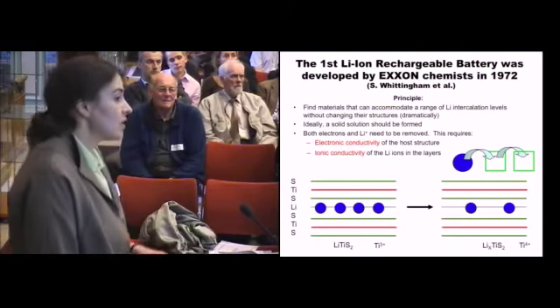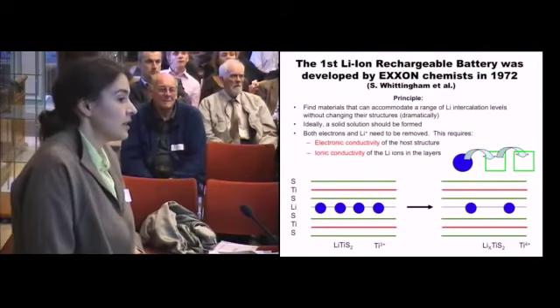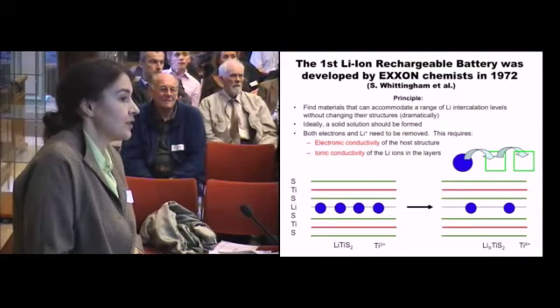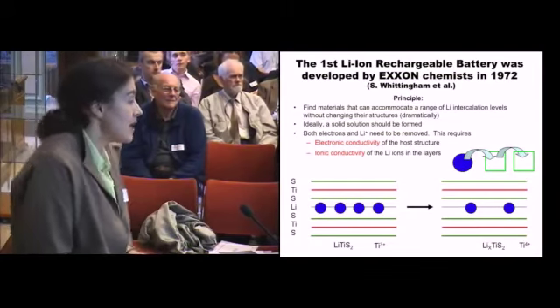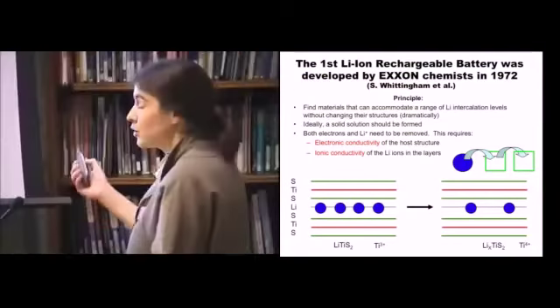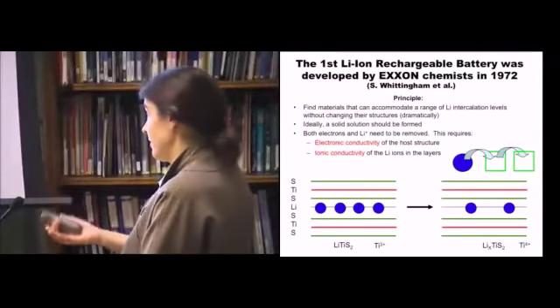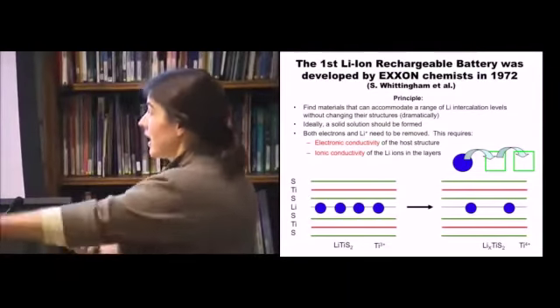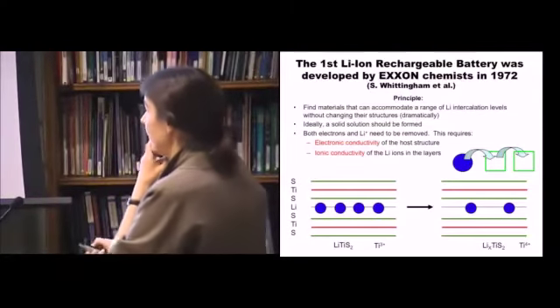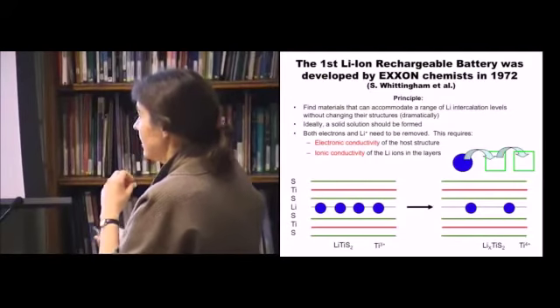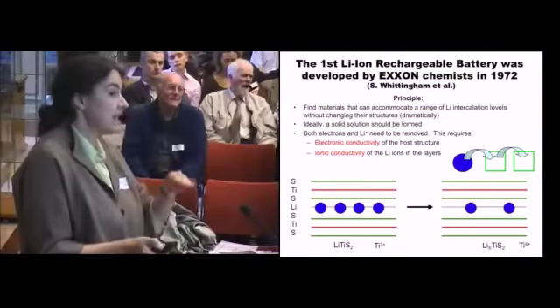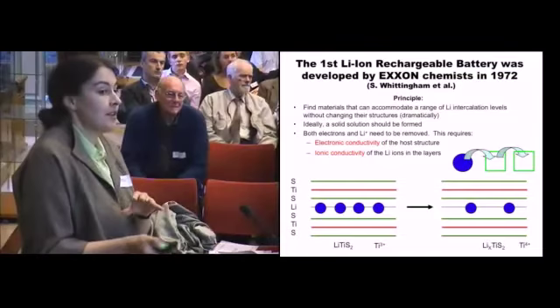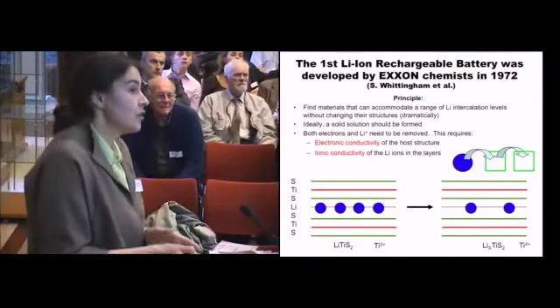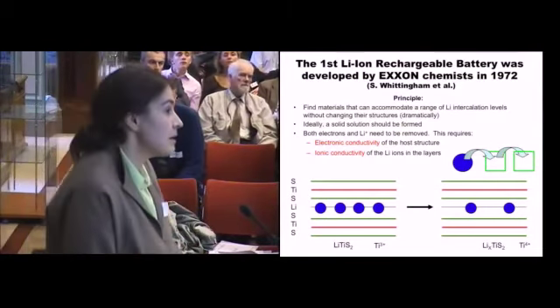And then when he charged it, so when he oxidized the titanium 3+ to 4+, the lithiums came out of the layers. It's a bit like squeezing a sponge cake and pushing out the jam from the middle. He could form the layers, in this case, retain their structures, but the lithiums came out. And you could do this backwards and forwards for many, many times.